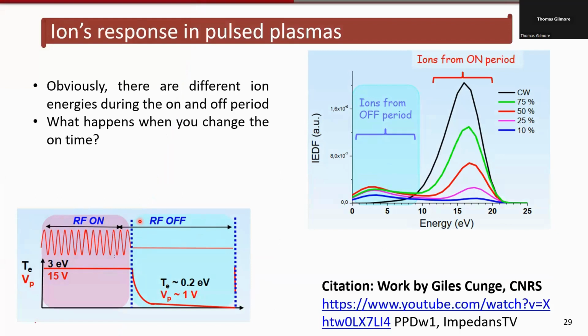There are also other benefits to pulsed RF. The same concept is used in HiPIMS. If you're familiar with HiPIMS, you have a really, really short on time, microseconds, tens of microseconds, with really, really high powers to get a maximum ionization fraction. And then the plasma is off for a long amount of time. So the average power applied to the electrode is reasonable, but the instantaneous power can be really large.